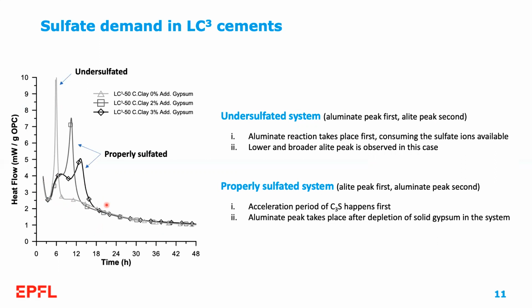Fortunately, there is an easy solution for this, and we have known this for more than 100 years. We can add gypsum or another sulfate source to the system in order to retard this aluminate reaction. And in this case, the silicate or alite peak takes place first, and the aluminate peak follows. In this case, the silicate peak recovers its normal development, and the aluminate peak takes place after depletion of solid gypsum in the system, in what we call a properly sulfated system.